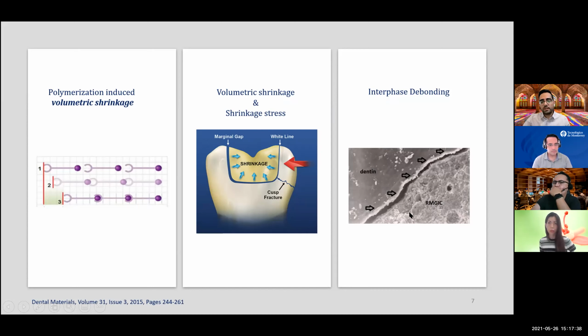And these are real scanning electron microscopic images of the dentin structure, the tooth structure, and the material that we used to restore the tooth cavities from tooth decay. And as you can see here, we have interface debonding, and it's not good at all. Because many kinds of bacteria can enter these interfaces, start their activities and produce problems known as secondary caries, especially if you have a restored tooth.